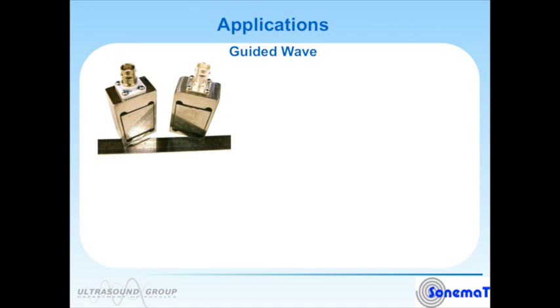When we construct transducers for generating SH guided waves, we usually have to completely encase them in a metal housing. We can do this by using a very robust, low electrical conductivity metal in front of the coil, such as perhaps titanium or stainless steel. We'll also usually make the body out of stainless steel or a similar material to make the devices robust. Some of these EMATs operate at depth below the sea.